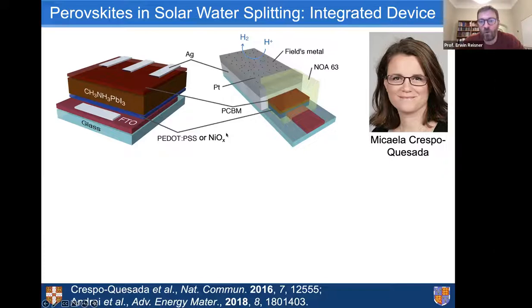In this case, nickel oxide, for example, is for us now the best hole transport layer. You can also use some conducting organic polymers, such as PEDOT:PSS, which you will find very frequently. The nickel oxide you can just grow on top of the FTO, the PEDOT:PSS you can just spin coat on top of it. And then you can deposit your perovskite, also just from a precursor solution. And then comes a PCBM. PCBM is a derivative of a Buckminster fullerene. That's just a very well-established electron transport layer, also just coated on top of your perovskite. And this really is it. And all you need then is silver as a connector.